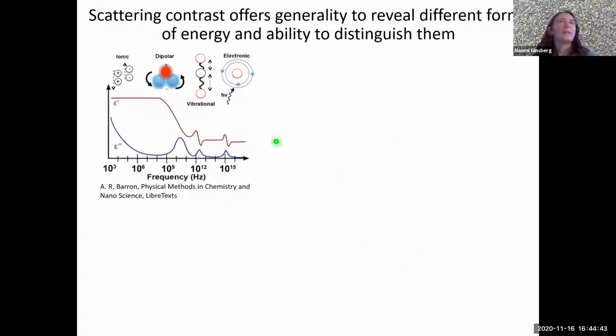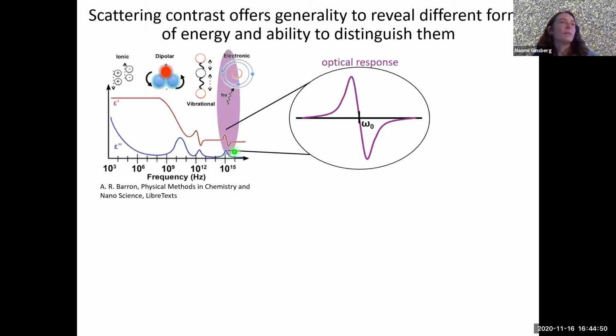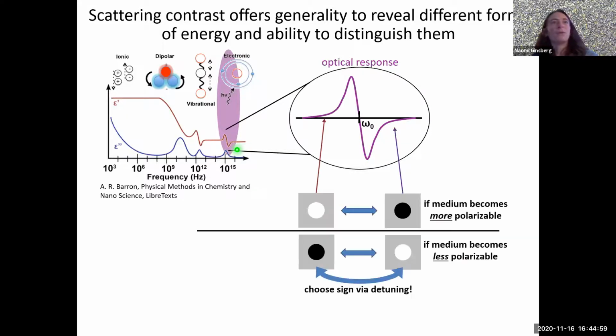Okay, so in our experiments, because we're probing in the optical, we're interested in looking at changes to the optical response that we might measure in the ground state on account of the presence of these quasi-particles. And so the reason that we might see a dark contrast in our microscope would be if the medium becomes more polarizable in the case where there are quasi-particles present, and we're sitting on the blue side of the resonance.